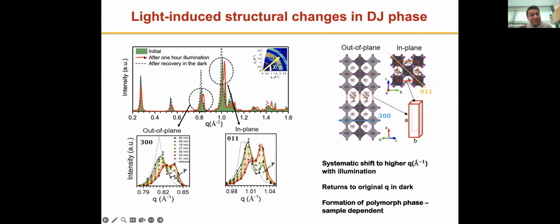What we found is that as we keep illuminating the samples, the entire pattern actually shifts to a higher Q value. And this is a reversible effect. So when the light is on, you get this, and then when you take the light off, after some time this relaxes back, which is shown as this dotted line. So the green is the original one.